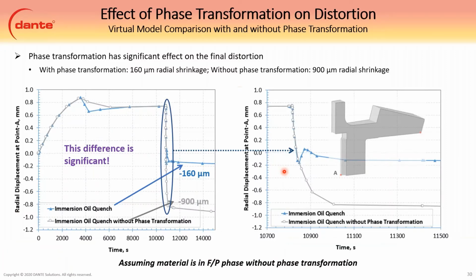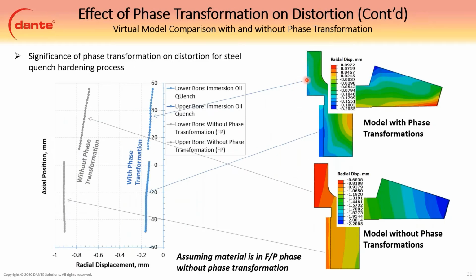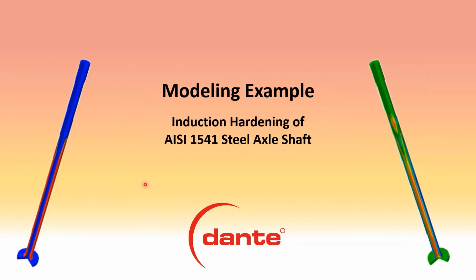This is just a model, but it clearly shows that without phase transformation, we get 900 microns of shrinkage. As we expand the martensite, and you can really see it in this curve, it reduces the shrinkage substantially. Right, 740 microns is huge. And that's looking at this point down here on the spline. And if we plot the top portion of the inner bore and the bottom portion of the inner bore, you can see the difference. You get essentially the same shape, but it's tremendously different in the amount of radial displacement. So phase transformations do make a huge difference in the final distortion. Huge difference. Okay, so that is it for the Dante portion of it.